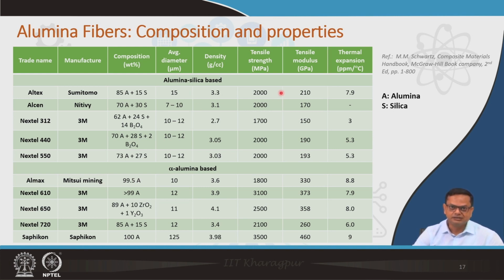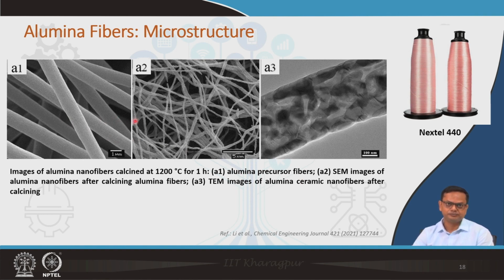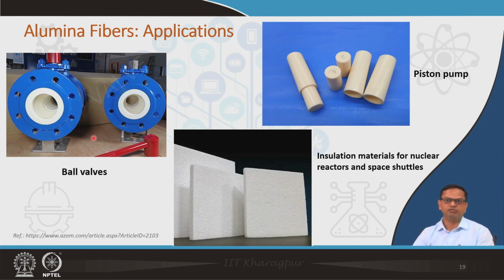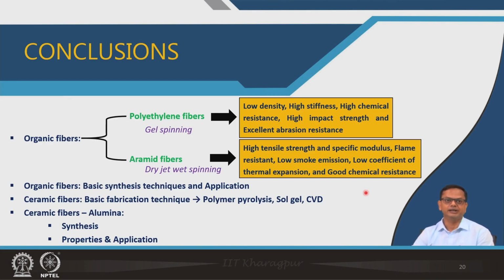And then the basic point to take from here is that it has very high tensile strength. Okay. In the range of 2 GPa to 3.5 GPa, so quite high tensile strength, and modulus is also in the range of 200 to 400 GPa, depending upon the ultimate final product. So, again you can achieve very high strength, high modulus, and a wide range of properties. And you can see here how alumina fiber looks like. Okay. Yeah, a spool you can see here, Nextel 440 spool, continuous alumina fiber, and applications as you can see in ball valves, in piston pumps, in insulation materials for nuclear reactors and space shuttle. So, exotic applications again. Okay.